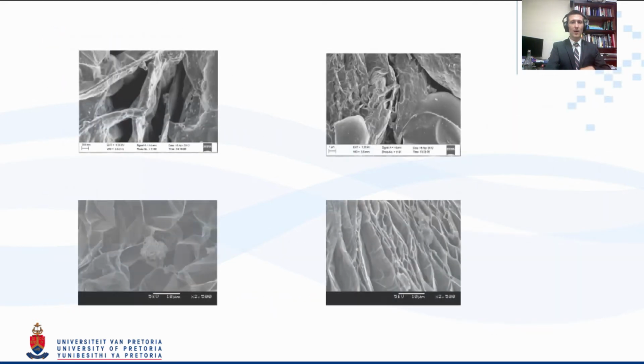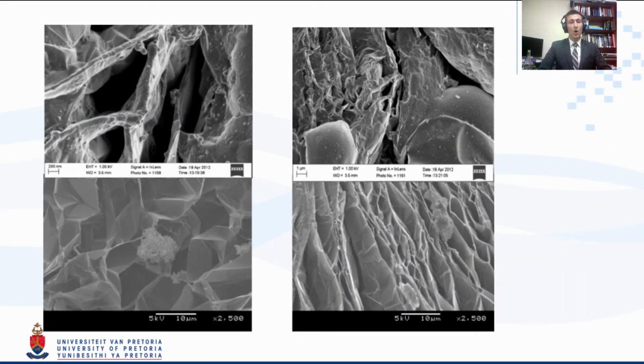So here I'll show you two of the SEM micrographs that we took. The two above and two below are distinctly different. You'll see that there are very sharp edges in the two below SEM micrographs, whereas the ones at the top have a round edge behavior. This is actually exactly what we wanted because the bottom one is pure expandable graphite and the top two micrographs show the glossy coating that this expandable graphite has gotten all over every little bit of its surface, even on this micron scale, which gives it a bit more sticky, cohesive structure.